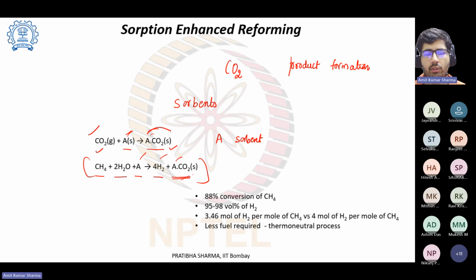So the conversion of methane is 88%. The purity is 95 to 98 volume percent of H2, and 3.46 moles of hydrogen per mole of CH4 versus 4 moles of H2 per mole of CH4. So in the steam reforming, you can get 4 moles, but in this you can get 3.46 moles of H2. Less fuel required and a thermoneutral process.